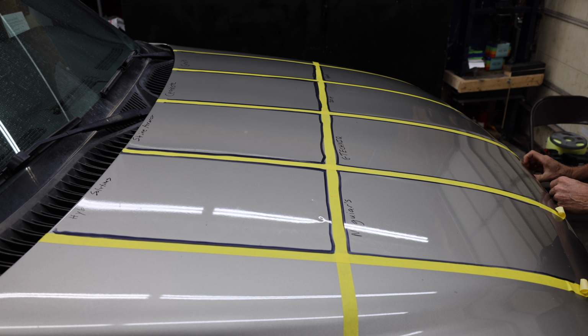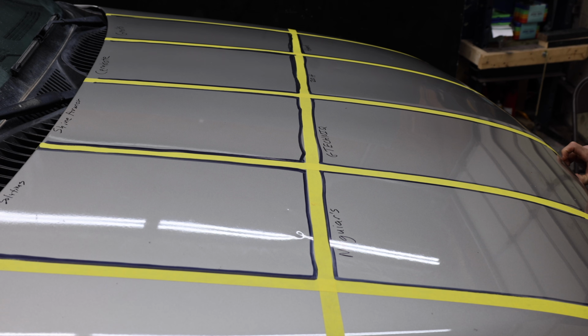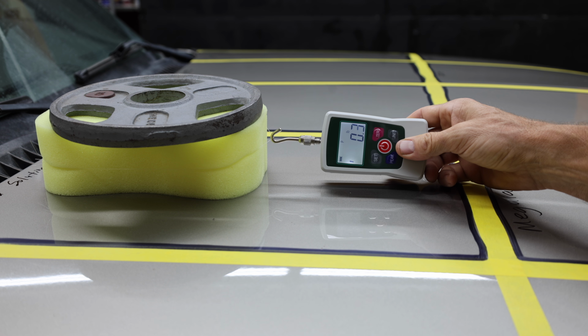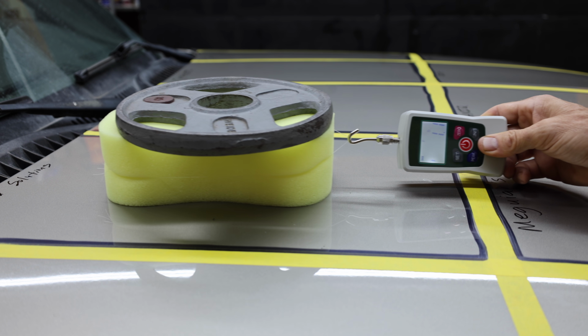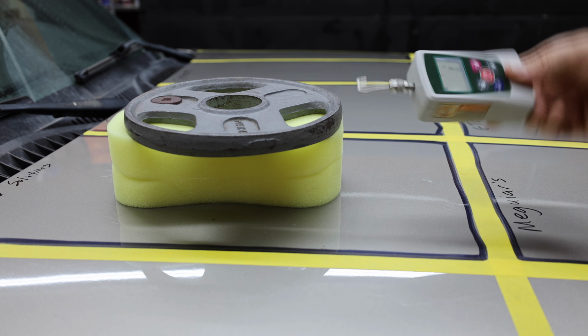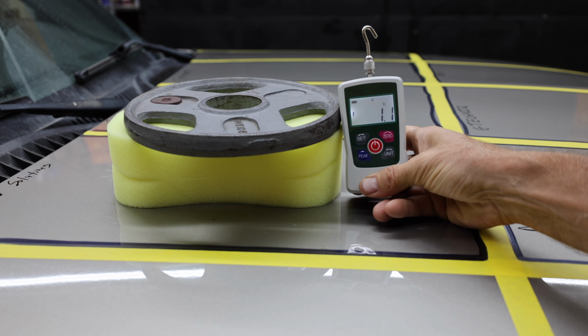All of the products have had 24 hours to cure in a temperature-controlled environment that's around 78 degrees Fahrenheit. Let's once again measure the slickness of the paint. The Hybrid Solutions is a lot slicker than the bare paint at only 1.1 pounds of force to slide the sponge.